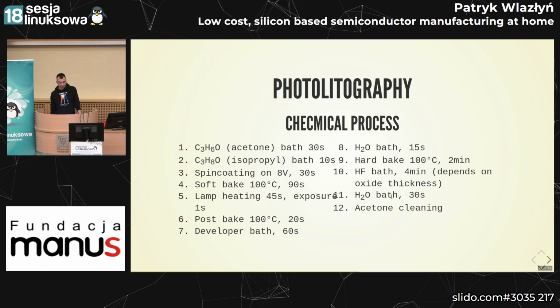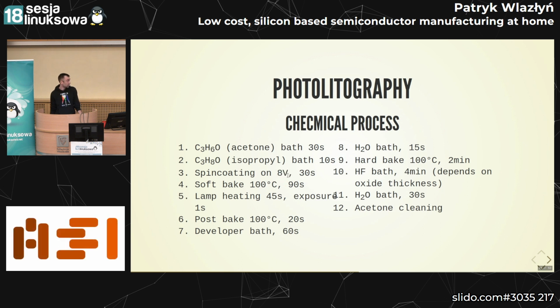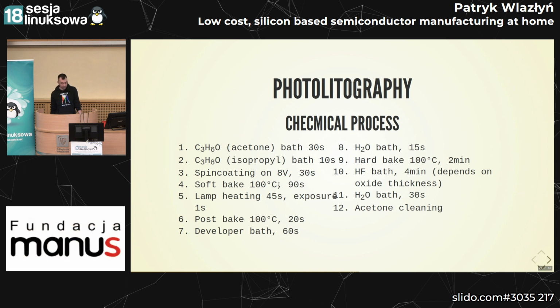But let's go through the chemical process first for the photolithography. It's kind of long, but let's go through it. So first we do an acetone bath to clear all the residues on top of the wafer. Again, isopropyl bath for 10 seconds. Then we spin coat a photoresist on top with the 8-volt supply to the computer fan for 30 seconds. We then do a soft bake on a hot plate at 100 degrees C.